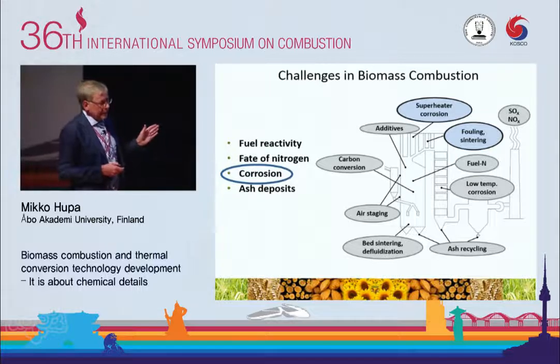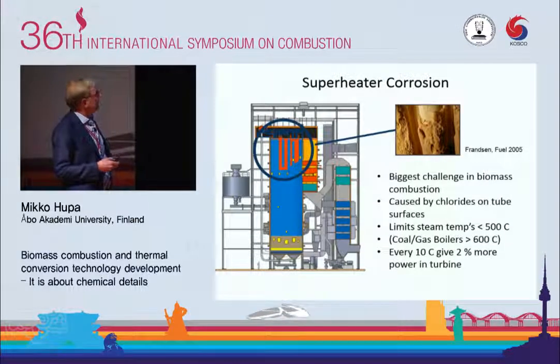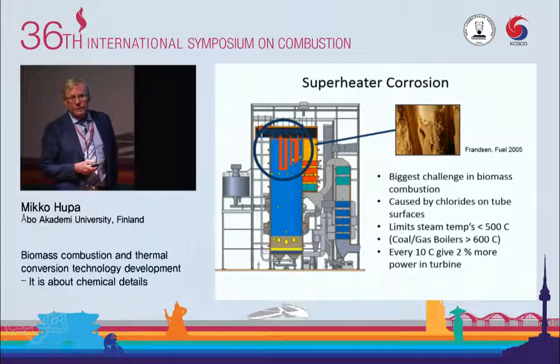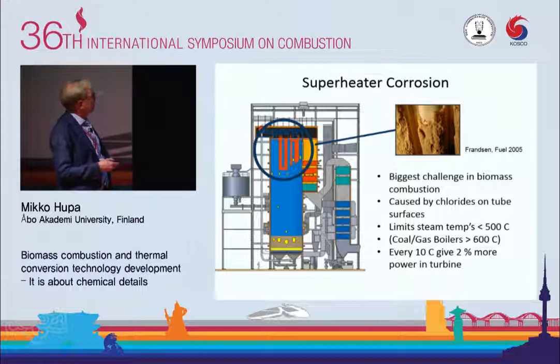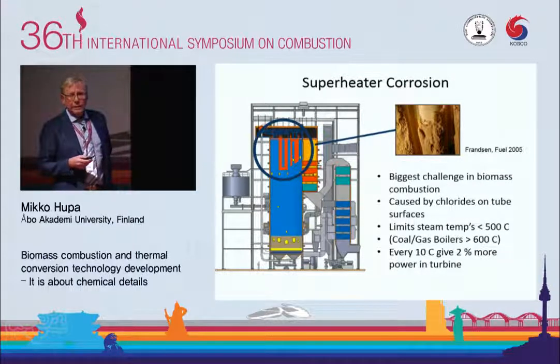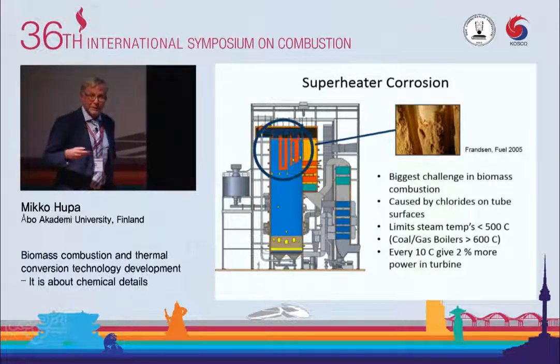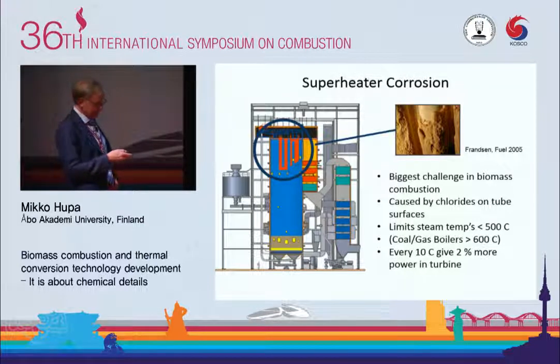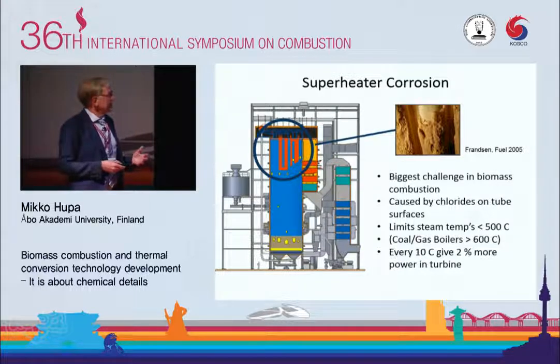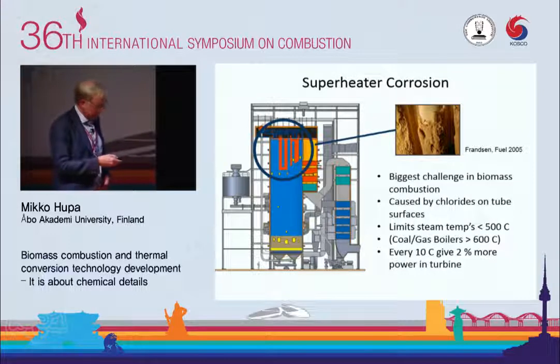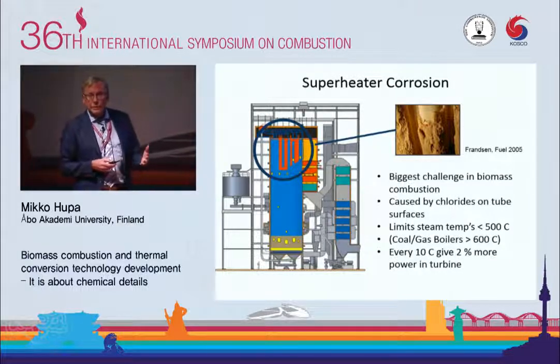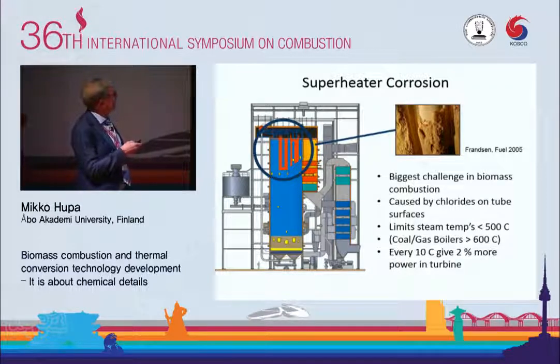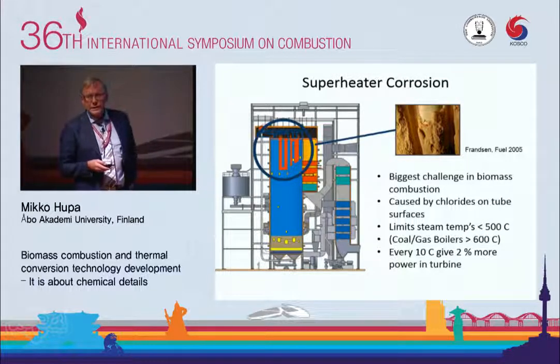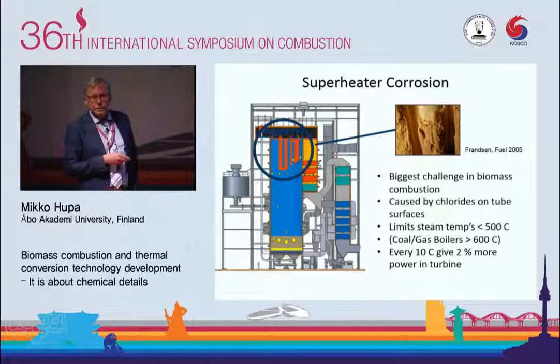Corrosion, a very important part of biomasses. And in fact, that's the biggest challenge in the technology development for these boilers. It's caused by chlorides on tube surfaces. That's quite clear. There everybody is agreeing, but then I will tell you later that we don't agree about all the details of this corrosion. This is the reason why the steam parameters are much lower in even the most modern power plants of this type. 500, 520 degrees is a very high number if we burn biomass fuels.